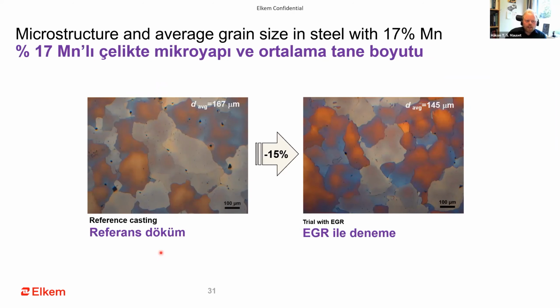So first we have the microstructure and average grain size in a steel with 17% manganese. This is the reference casting. You see the average grain size is 167 micrometers. With EGR, there was a 15% reduction in size. So the average is about 145 micrometers.